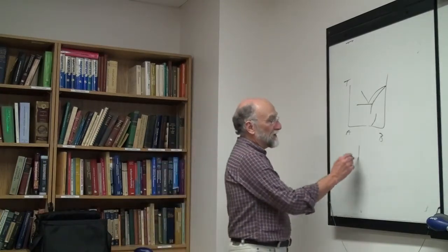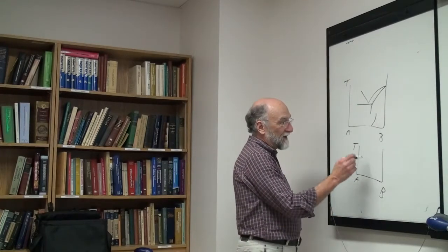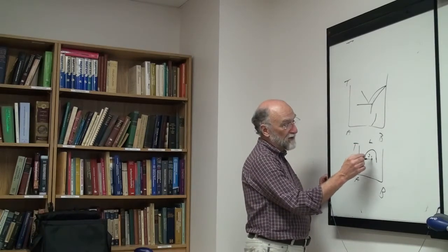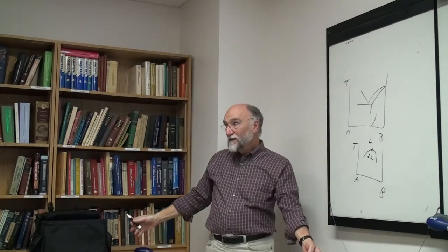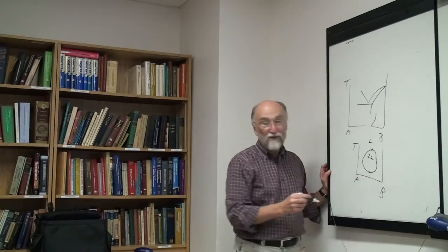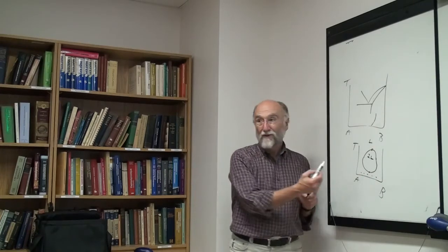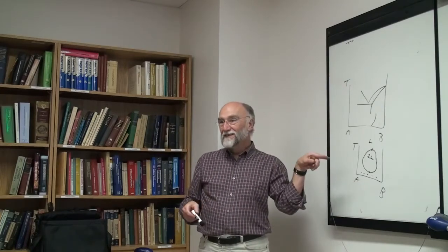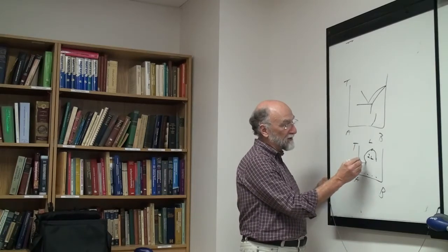You can even see miscibility gaps. I've never seen them in a metallic system, but in a temperature-composition diagram, normally you have a liquid and then two liquids, and this is the critical point of your miscibility gap, which then gets wider and wider. But you can actually get this coming around like that, and you can have a lower critical temperature. Here the liquid is completely miscible, and as you heat it, it becomes immiscible. I think water and nicotine actually looks like that. I've also seen some that don't go all the way, but come in like this and then come back out again.